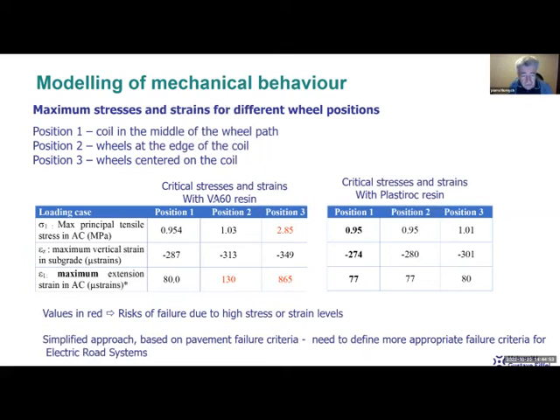And what we found is that if you use a very soft resin, in fact, you have a soft support under the surface asphalt layer, and you increase a lot the strains and the tensile stresses and the tensile strains in the asphalt layer, especially for position 3, where the wheels are centered on the coil. Here you get a very high tensile stress and a very high tensile strain. But if you use a resin and a block also for the coils with a modulus very similar to the asphalt layer, with properties very similar to the asphalt layer, we have no strain contrast between the asphalt layer and the block. And then you have much less influence of the block on the stresses and on the strains.